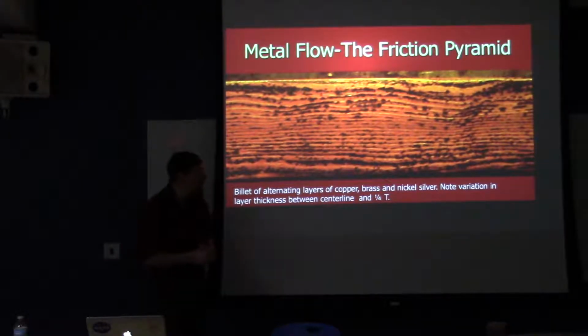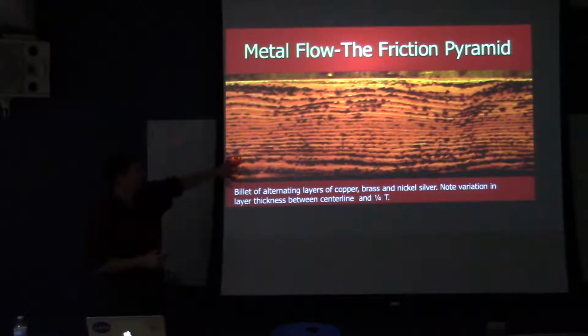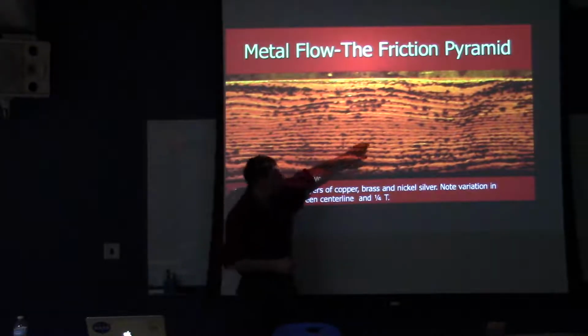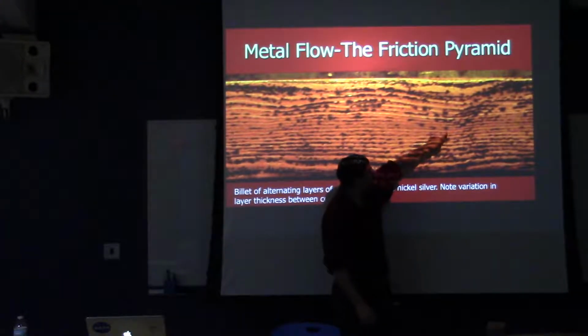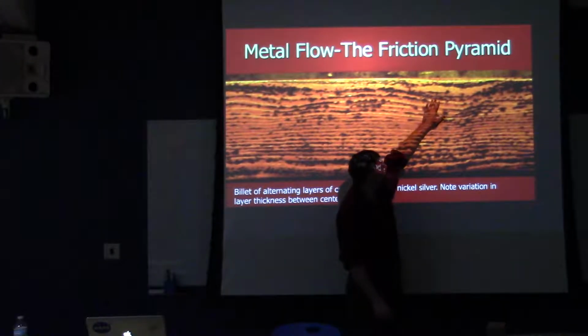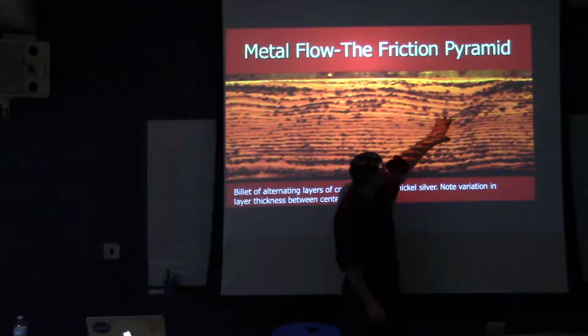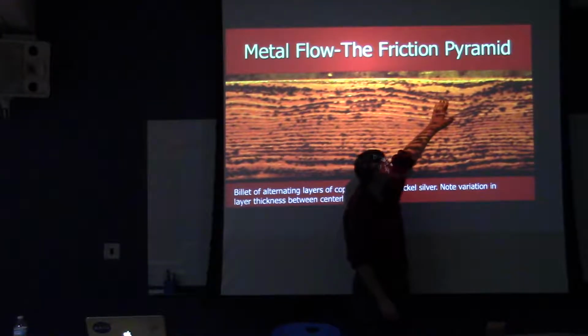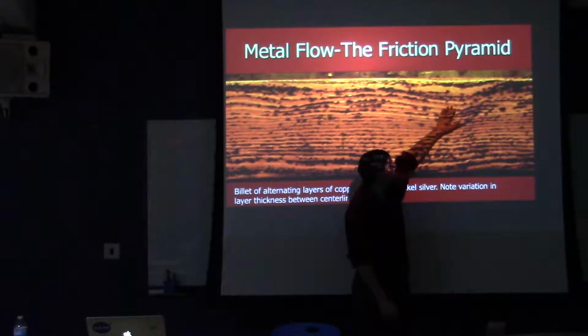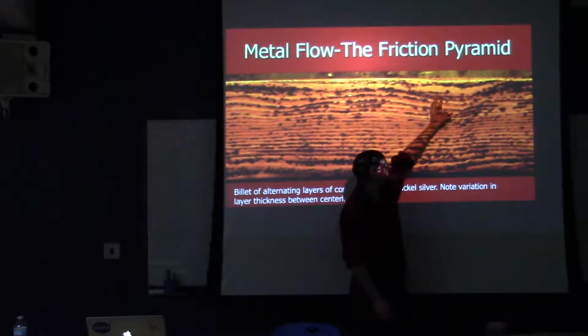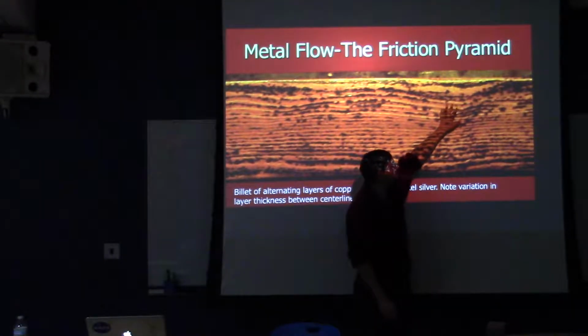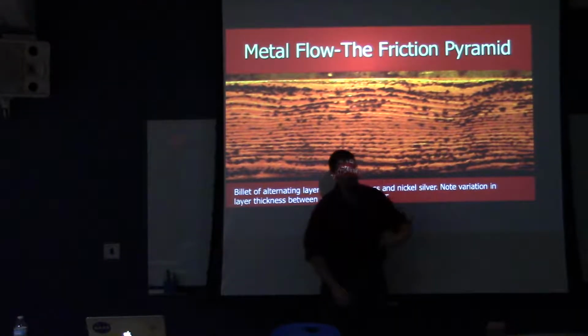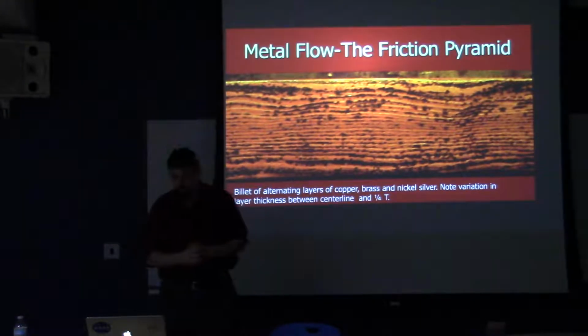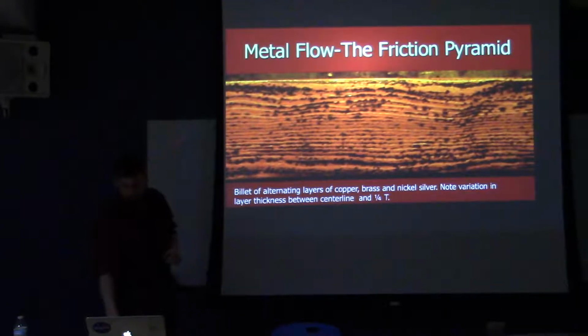Here's an example of some laminated metal that shows you these friction pyramids, and you can see the differences in layer thickness along the center versus up here. This is one where the friction pyramid has collided and caused deformation to occur here, and up here we still didn't have much effect. The friction from the die that's in contact with the work is still acting on this metal here and keeping those layers closer to their original starting thickness.